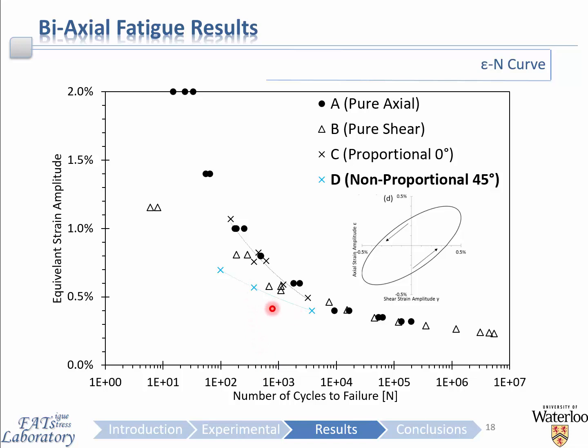So as can be seen by these blue data points as shown here, this is typical of ductile materials that observe a degradation in fatigue life as a result of the non-proportionality effect. And this material is ductile as it has a 20% failure elongation, so this is fairly typical, in line with what other researchers would find.